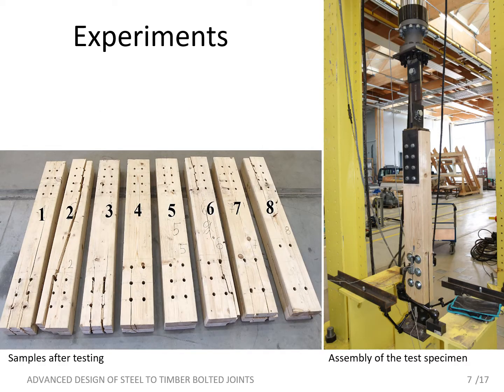In this picture on the left, you can see all 8 samples after the test, and the whole experimental setup is on the right. For example, sample number 2 has a long crack all along the sample. Sample number 4, 6, and 7 have some small cracks, and sample number 5 has almost no visible cracks. The whole experimental setup before the beginning of the test is on the right.